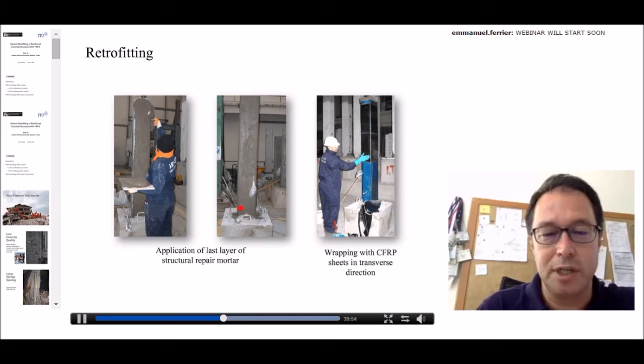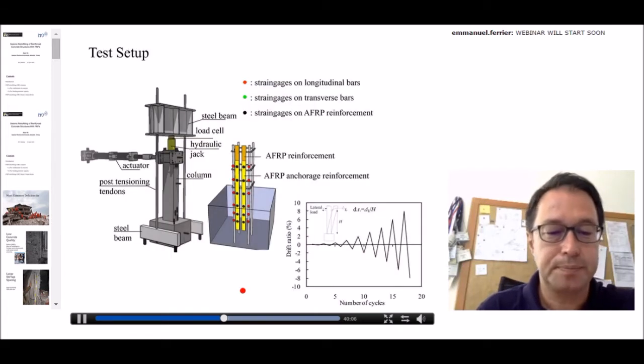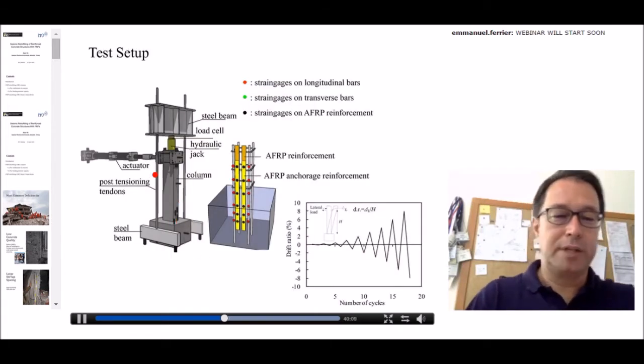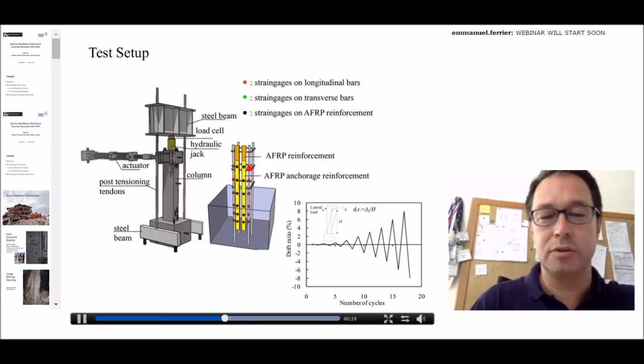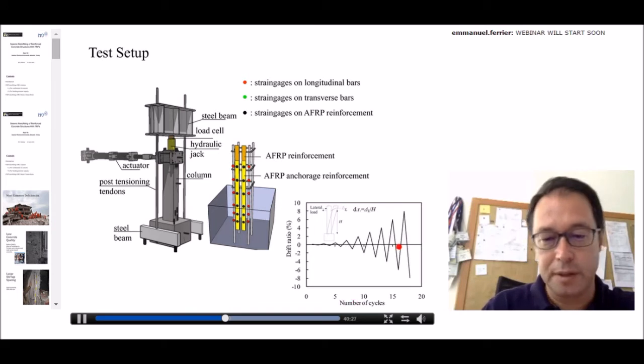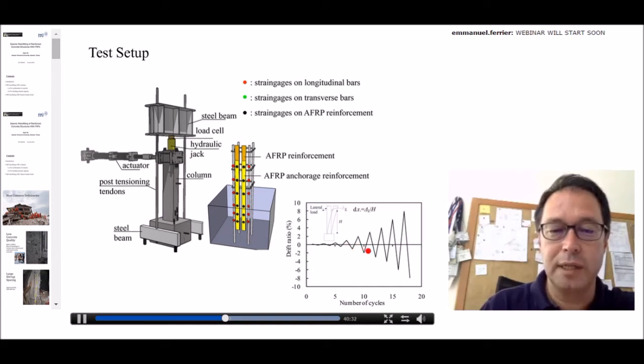The final stage, as I said, since we have increased the flexural capacity, to avoid shear problems, we just apply a transverse jacket by CFRPs to improve shear strength. The test setup is quite similar to the works that I have shown you. We have reverse cyclic lateral loads here, and axial load here, which is kept constant. Here you can see the locations of strain gauges on FRP reinforcement, anchorages, or the main steel bars. This is the loading system as often done. We apply the reverse cyclic displacements in two directions in a quasi-static fashion.